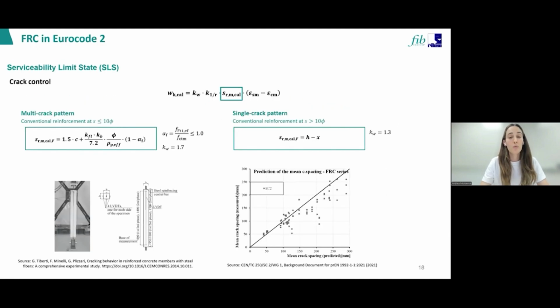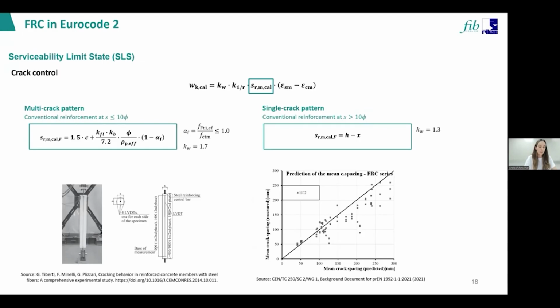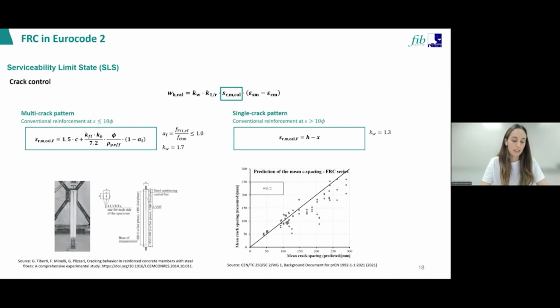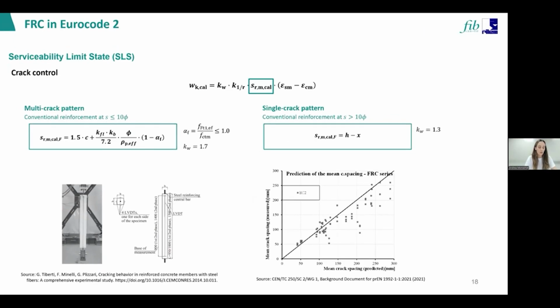If we move to the serviceability limit state, one of the most recognized benefits of steel fiber reinforced concrete is the ability to reduce crack spacing and crack widths under service conditions. So in Annex L, this effect is mainly introduced through the modification of the mean crack spacing formulation used for plain concrete. Depending on the reinforcement arrangement, the code distinguishes between multi-cracking patterns and single crack patterns. In the case of multi-crack patterns, the mean crack spacing is reduced through a parameter accounting for the crack arresting